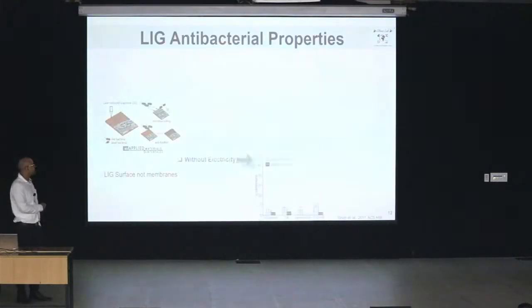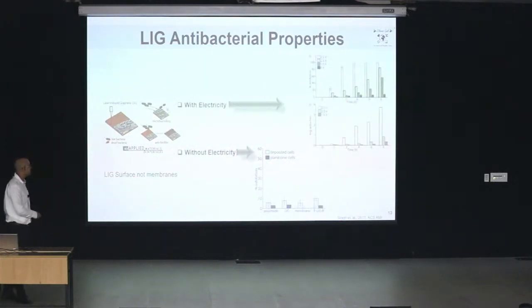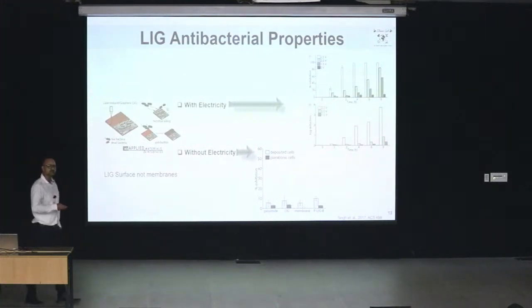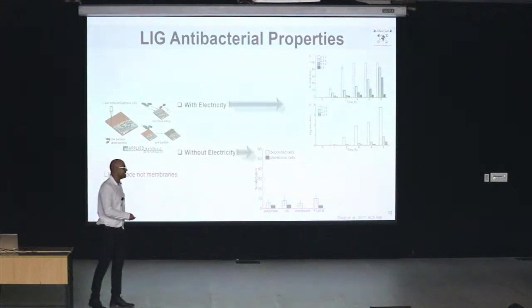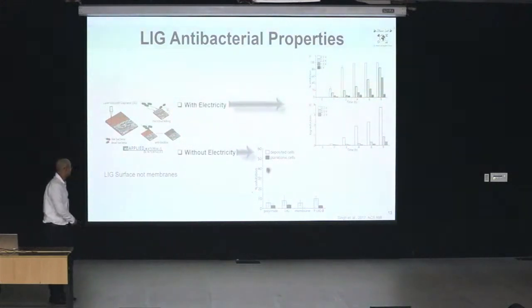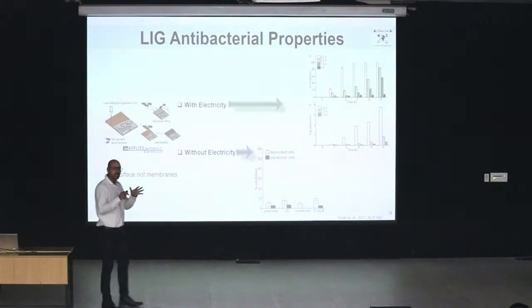Also, when we did the electricity experiment, without electricity you can see we haven't found any toxicity of these graphene surfaces to microorganisms. But when we applied electricity, you can see with 2.5 volt in 9 hours we have seen 6 log removal, which has shown that with electricity this surface can be very lethal for the microorganism, but without electricity it's not killing, but this 3D texture can repel the microorganism. So it's an antibiofouling surface without electricity, and with electricity it's an antibacterial surface as well.